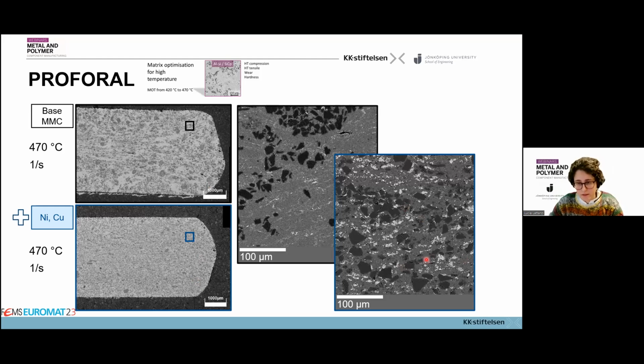There is a little bit of flow, but much hindered by the presence of such phases that are stable at high temperature. You see that they start to get not disintegrated, but reduced into smaller parts, but they're still there and they can interlock and hinder the material flow.